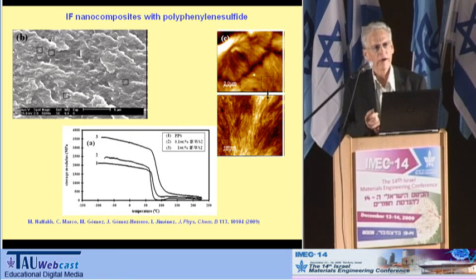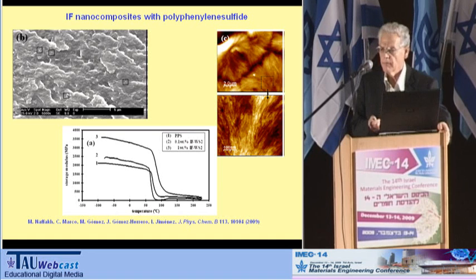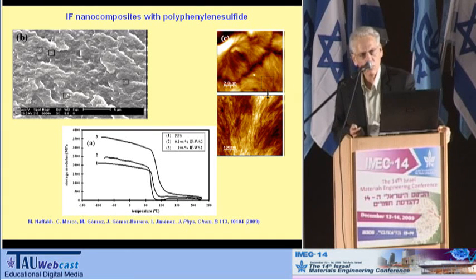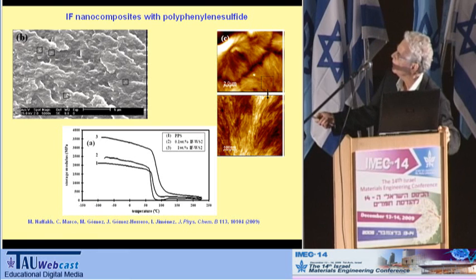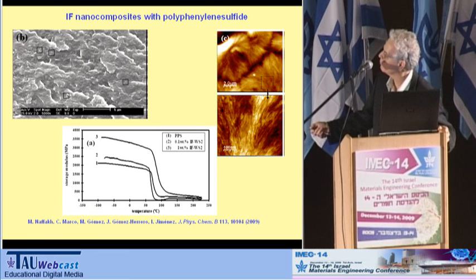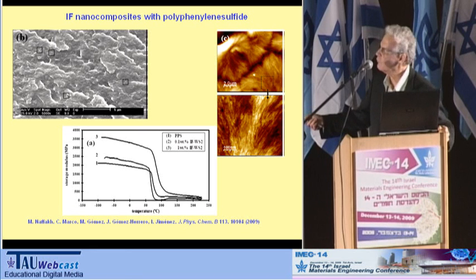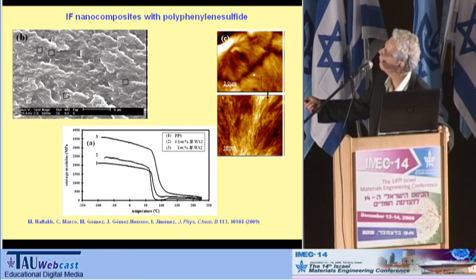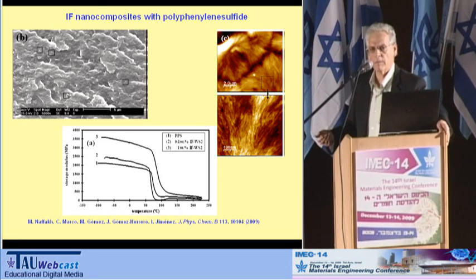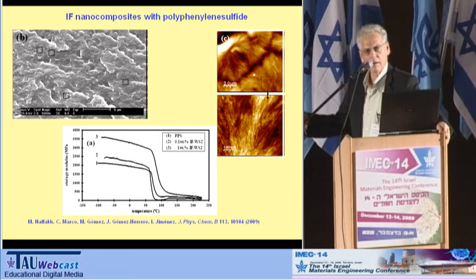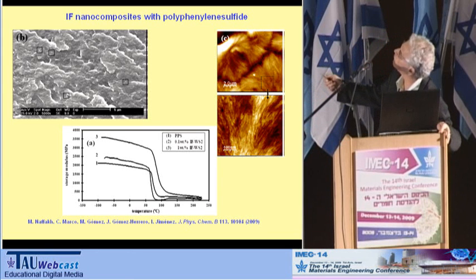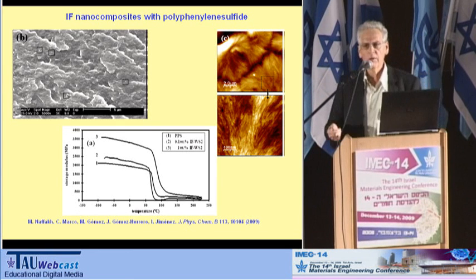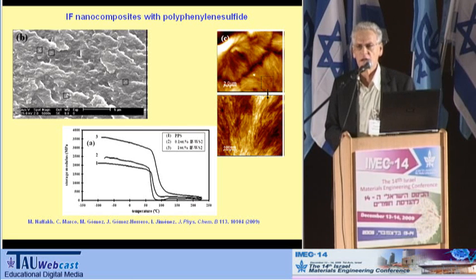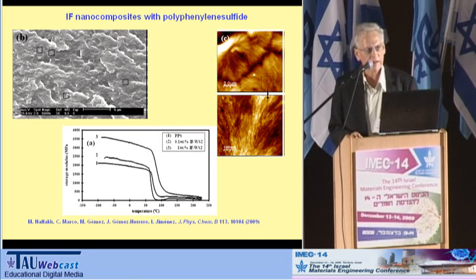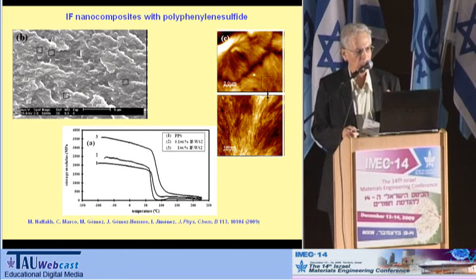In another direction that has started just 3 or 4 years ago, not more, these nanoparticles are now added to a variety of polymer composites, making nanocomposites with enhanced mechanical properties. And you can see here a recent work published by a group in Spain, where the mechanical properties have been tremendously improved by adding very small amounts, 1%, of the IF nanoparticles into the polymer, which is in this case polyphenylene sulfide. There are a number of polymers now that are being investigated and developed. Each one has a different mechanism. The strengthening mechanism is not clear as yet.